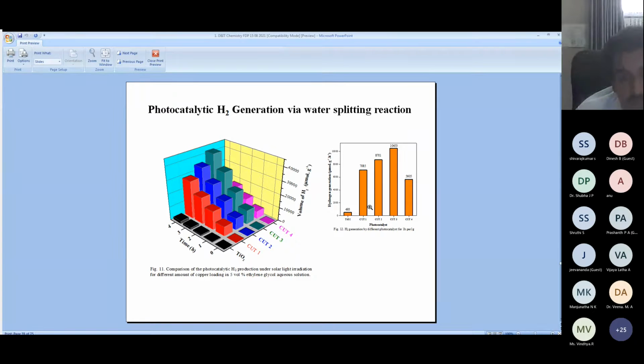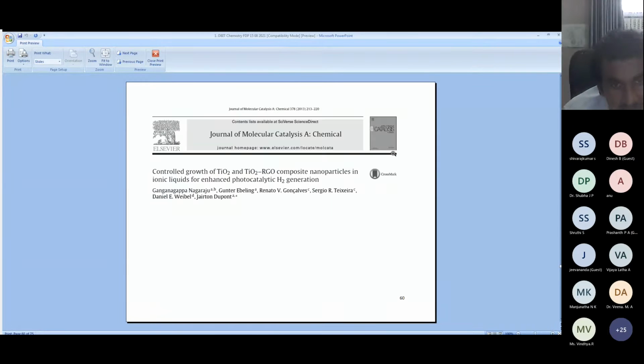For that, when you're looking for the reason why, as the concentration of copper increases, hydrogen generation increases, but after a certain stage, why does it decrease? Because as the energy gap between the valence band and conduction band becomes much smaller, the rate of recombination of electron and hole increases. At a particular point the rate of recombination will be less, but after a certain stage it increases, right? So at 4%, the hydrogen generation decreases. So we are going to say that 3% copper doping shows very good hydrogen generation, right?